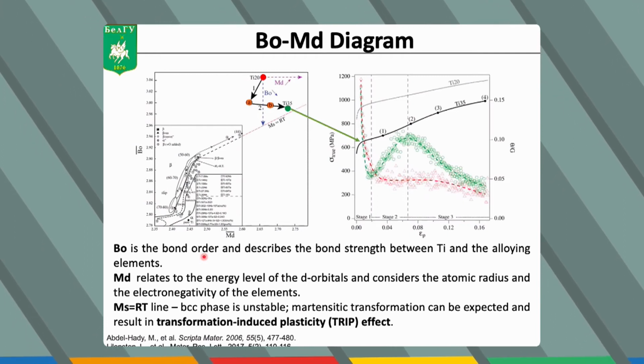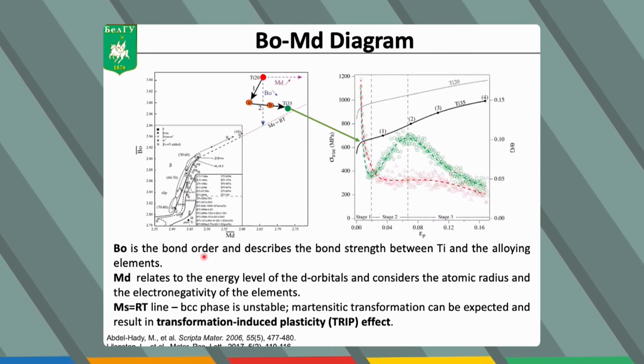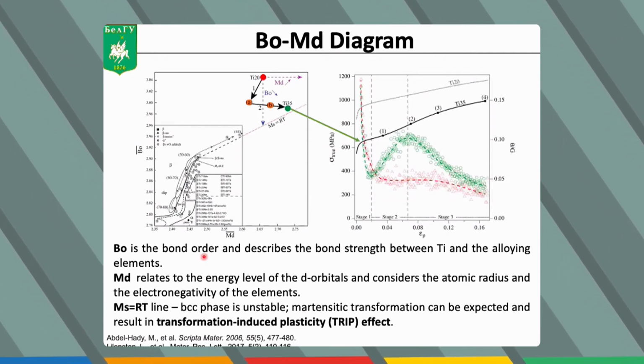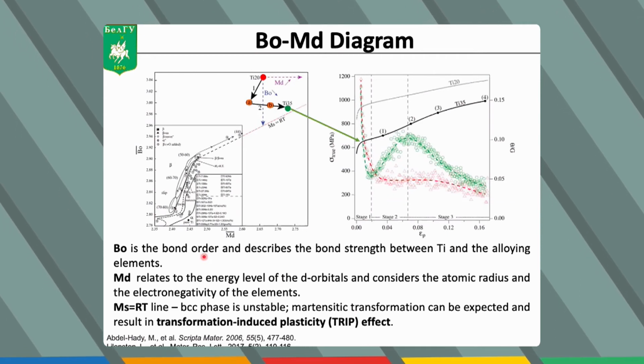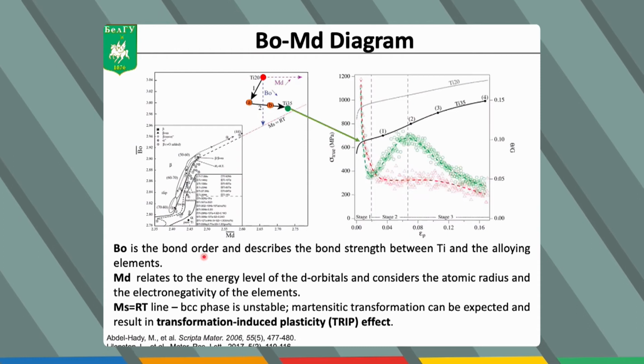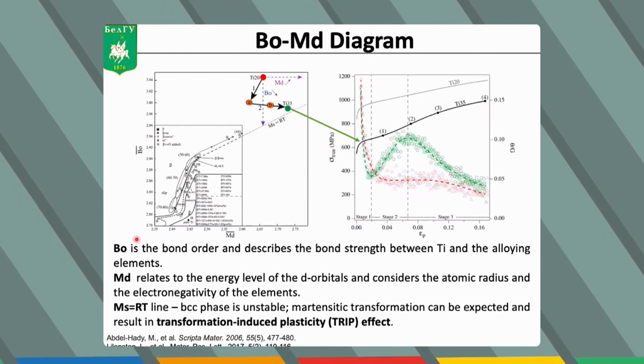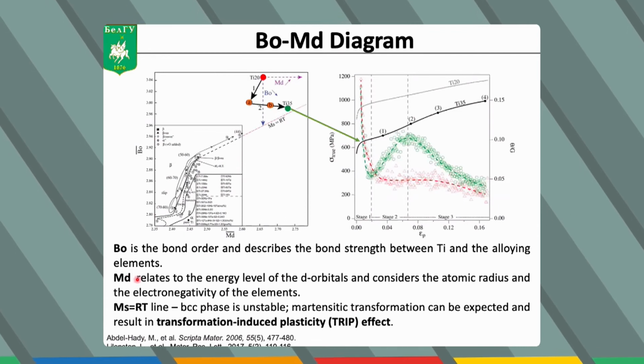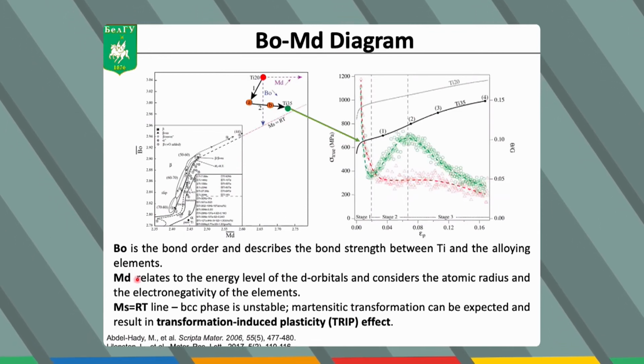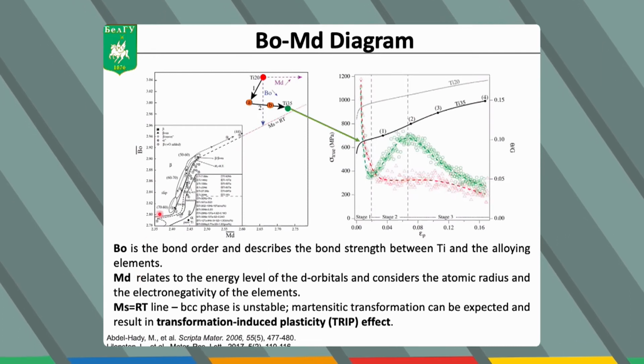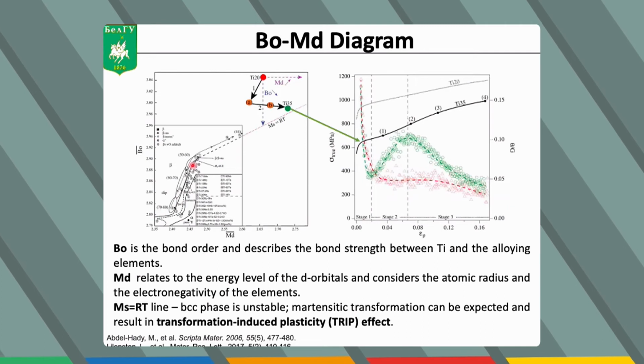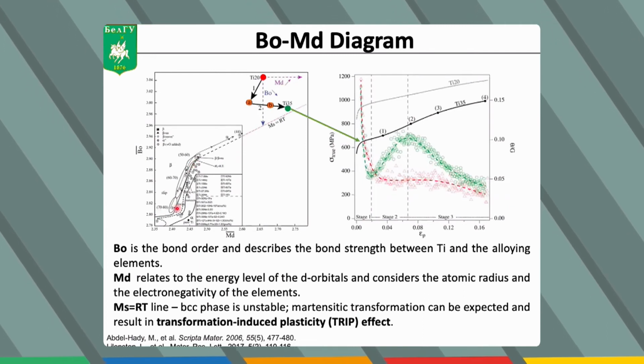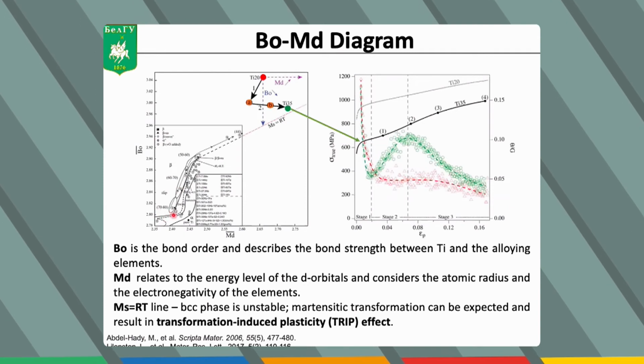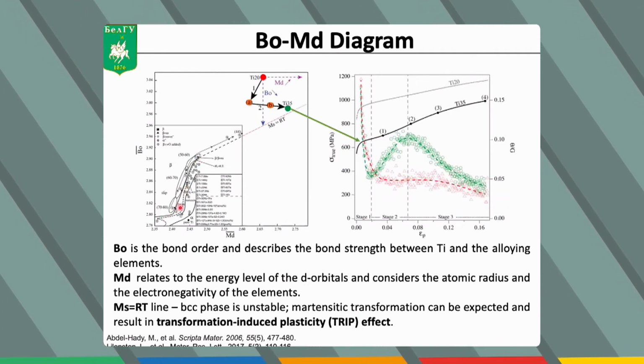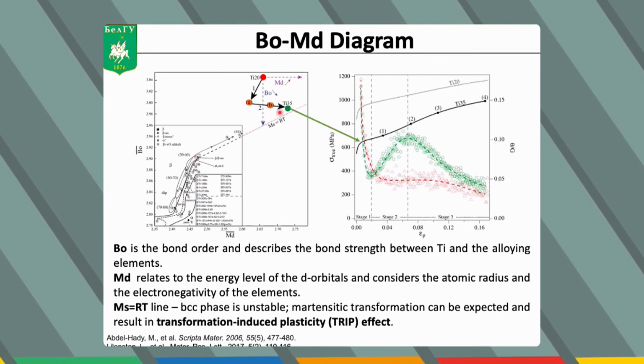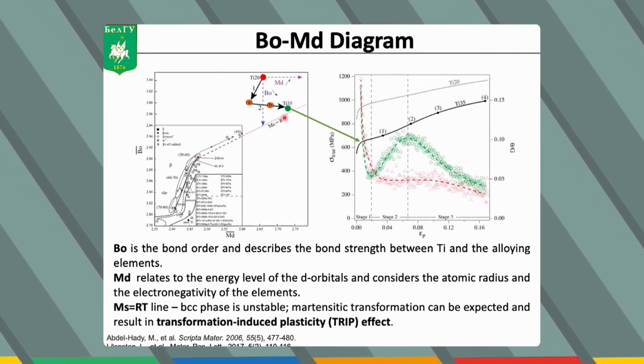And in BCC metals and alloys, the martensitic transformation occurs when the stability of the BCC phase is low. And the stability of the BCC phase is directly correlated to some electronic parameters such as Bo, Md. I won't get into much detail here, just the parameters of the electronic structure. And actually, for the conventional alloys like titanium alloys, a line corresponding to the instability of the BCC phase and the transformation-induced plasticity effect has been established. And quite recently, this line has been extended to the high entropy alloys regime.